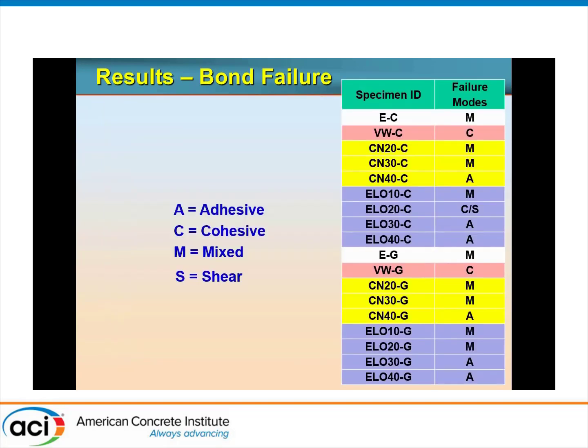So that's the failure modes. In fact, the epoxy carbon and epoxy glass were mixed. The VW was cohesive in both. The CN, again, was mixed, and adhesive when you had 40%. The EL, same actually for glass as well, MM and A. For the epoxidized linseed oil, mixed, cohesive, and shear. In fact, one of the repetitions failed by shear, and then adhesive. So the trend is kind of the same as in carbon and glass for each type of resin.